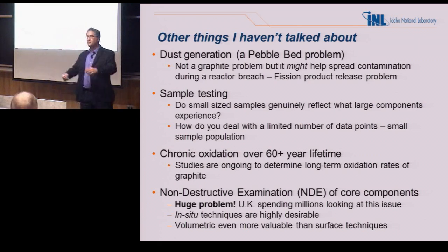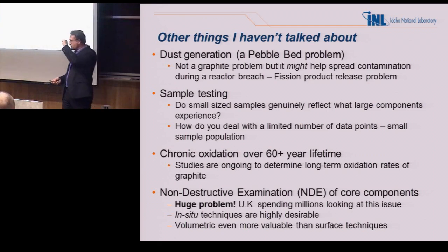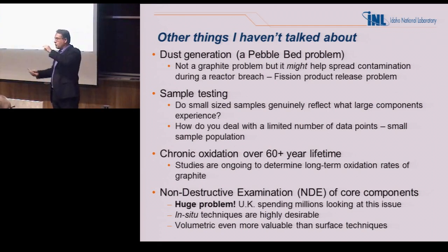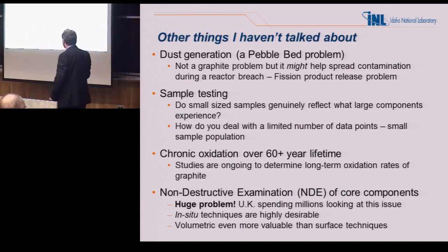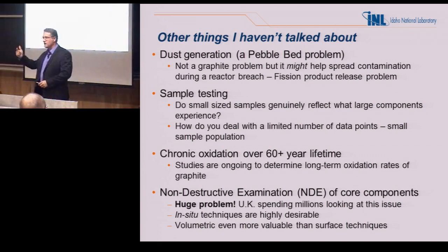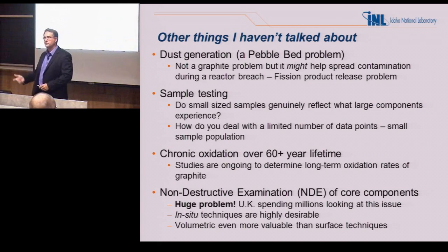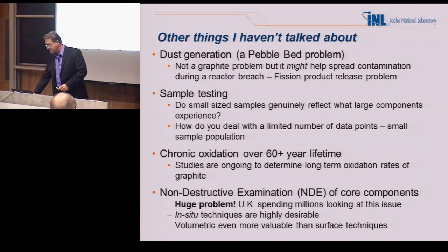Sample testing. How do we know when we take these small little samples that we put into the reactor really truly work with big, huge components? Makes sense. Chronic oxidation over the 60-plus year lifetime, it's different than the acute, folks. And there's going to always be a little bit of water, a little bit of air that's always trapped inside there. How does that affect it?